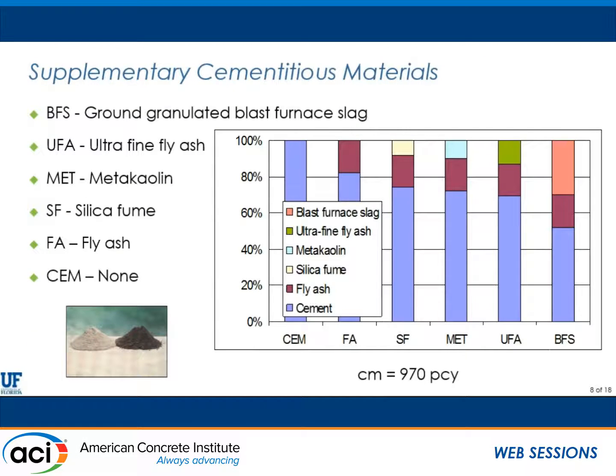So this followed a project or several projects with the DOT where they looked at doing physical tests and durability tests on concrete that's been made with supplementary cementitious materials. As I mentioned earlier, we have blast furnace slag, ultrafine fly ash, metakaolin, silica fume, and then fly ash was their standard. They have fly ash in all the mixes.